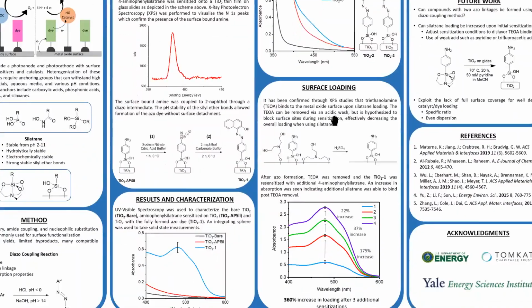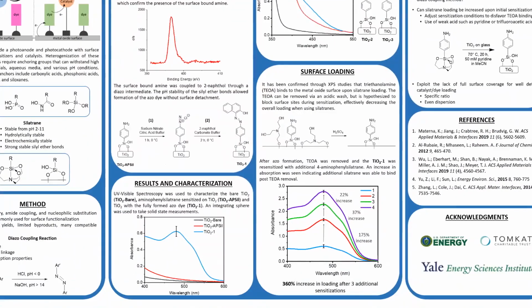Shifting gears now to surface loading. It is typically most favorable to load as much substrate as possible to the surface. It has been shown, however, that when using silatranes, triethanolamine also binds to the metal oxide surface, but can be easily removed via an acidic wash.